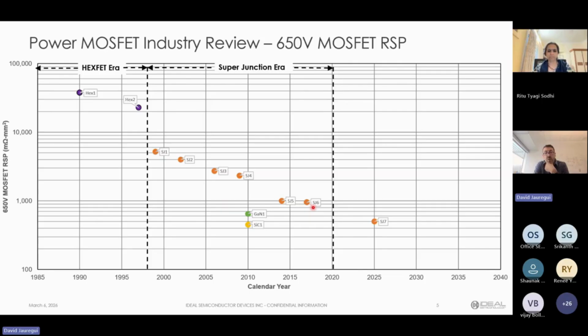The only drawback is that they significantly increased the cost. And at the time, like any technologies, GaN and silicon carbide was very expensive to manufacture. The quality was very poor. People had to reinvent how to do reliability testing because they were doing new materials. But the thought is, over time, things will get cheaper, and that's generally true for most technologies. But that's where Infineon landed with their latest super junction, and where GaN is today, for the most part, it's about the same when it comes to this one specific parameter.